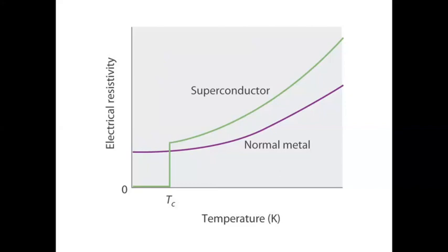But at the same time, if the energy is more, then sometime you will reach a condition where the mean free path of the electron will be of the order of the lattice constant, and at that condition, it can reach this criteria. Experimentally it will be evident from the saturation tendency of the resistivity plot of a material, particularly a metal, at a higher temperature. These are the two unique features.